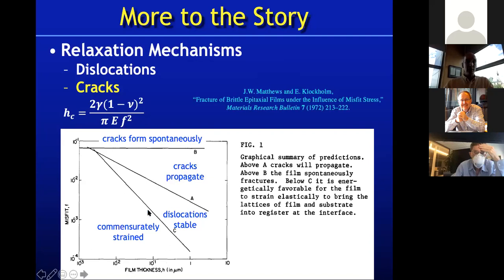In this lower left quadrant of misfit, 1% is here, 8% is about here. Okay, huge strains. The homogeneously strained portion where we want to be if we want to use the strain engineering is down here in this lower left. When one passes this first line, this is where one passes the equilibrium critical thickness for dislocations to come in, like I talked about in the last slide. So above line C here, it's now favorable for dislocations to form to relieve all of that strain, but there's a nucleation barrier for that to happen.